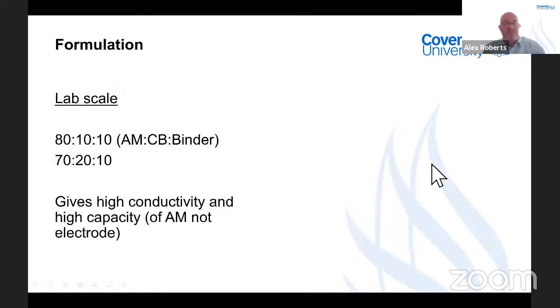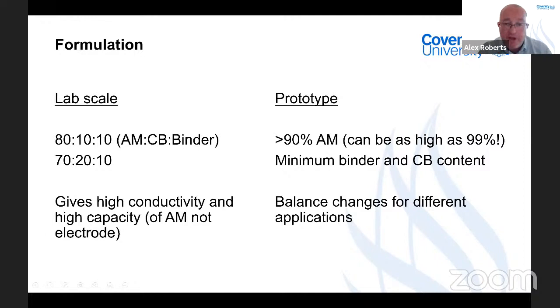So the formulation, typically in the lab scale, I think everybody at some point who has worked on developing a cell will have used either the 80-10-10 or 70-20-10 formulation, which refers to the active material, the carbon black or conductive additive that's put in there, and a binder. And this gives a high enough conductivity and a high capacity of your active material, but not for your electrode necessarily. When you go to prototype or production, you're looking at over 90% of your active material, but this can be as high as 99% in some very specialized cases. Incidentally, when you get to the 99%, that's when the adhesion starts to become a problem, and it's used in some very specific applications. So going through, you try and minimize the binder and the carbon black content and have as much active material in there.